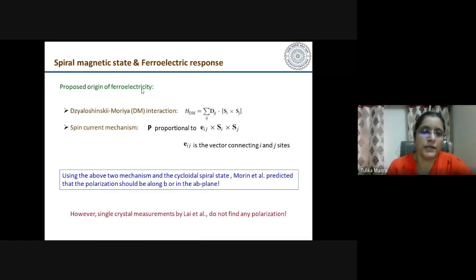Okay, so for the origin of ferroelectricity, Morin and others proposed this mechanism which is known as spin current mechanism, which needs that the Dzyaloshinskii-Moriya interaction has to be finite and the spiral state has to be cycloidal, and then one can have a finite polarization which is proportional to this quantity. If Si is the spin at ith site and Sj is the spin at jth site and eij is the vector connecting i and j sites, then the polarization is proportional to this quantity. So this is what is given by the spin current, which is called spin current mechanism. So using this spin current mechanism, and assuming that the cycloidal spiral state is present, Morin et al predicted that this polarization should be finite and it should be along B or in the AB plane. However, the single crystal measurement didn't find any polarization.